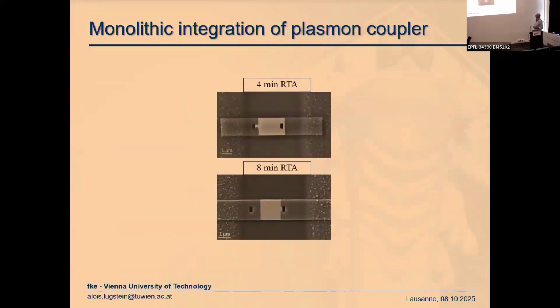Here you see the SEM. So this is after 4 minutes annealing. So the bright part is still silicon. So this is already exchanged. And if you continue for a further 8 minutes, these trenches are then in the aluminum. And again, you end up with a very sharp interface. So also on this side, finally, we'll have a sharp interface, and these holes also positioned in the aluminum.